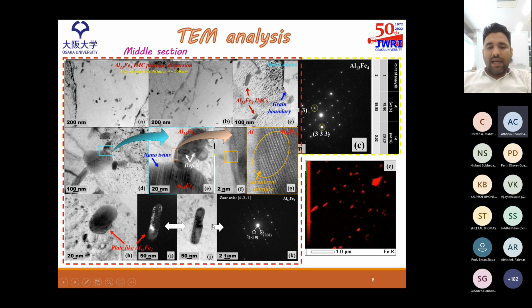Now the interesting thing is that the elliptical shaped particles are very small, so they can contribute in the grain pinning mechanism, or the Hall-Petch mechanism, to restrict the grain growth. Whereas these large particles help in particle stimulated nucleation. They provide the sites for the heterogeneous nucleation in the solid state for the grain. So in these two ways, these contribute in the grain refinement.